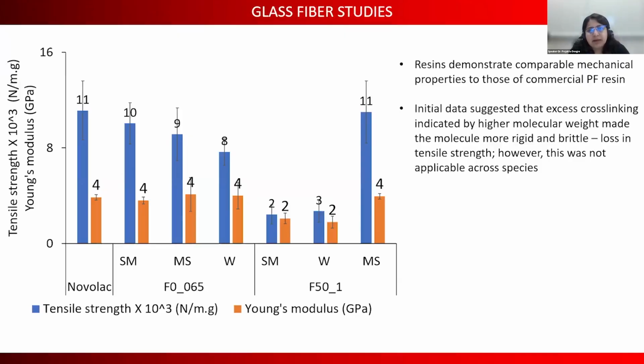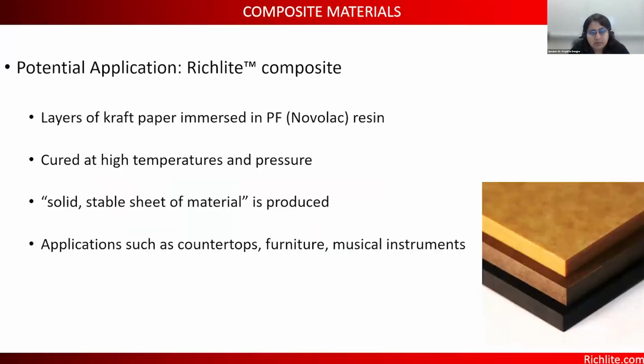So once we had an idea that our resins were actually performing quite well with the commercial Novolac resins, we decided to test out some other applications. So the first application that we tested was the Richlite composite, which is a commercial product. The idea behind this is that they used kraft paper from the paper industry. Several layers of the kraft paper are immersed in Novolac resin, and then they are cured at high temperature and pressure. And then you get a solid, stable sheet of material, as you can see in this picture, which can be used in several applications such as countertops, furniture, musical instruments.